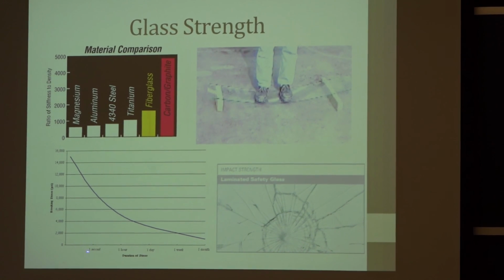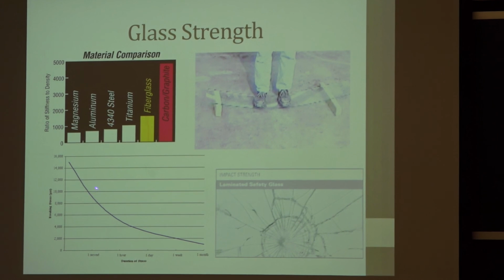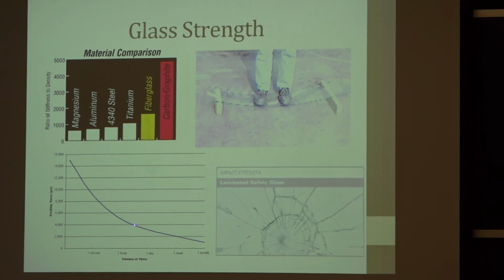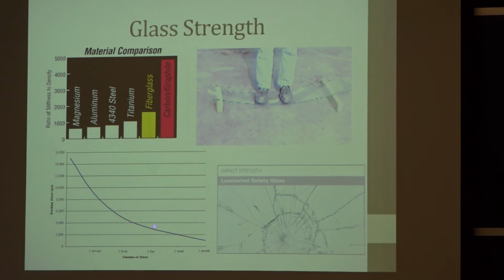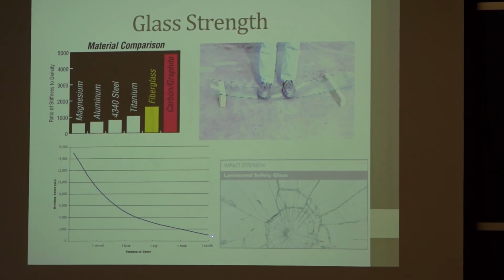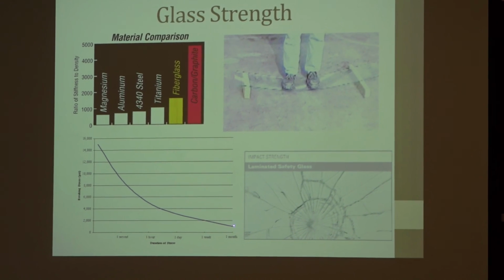And within 1 second, it drops down here. And within an hour, it drops down to 1/3 of the original value, a day, a week, and a month. It's down to 1,000 PSI, not as good as most plastics, okay?